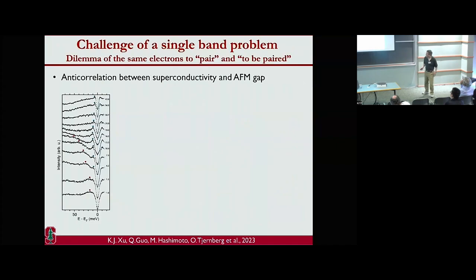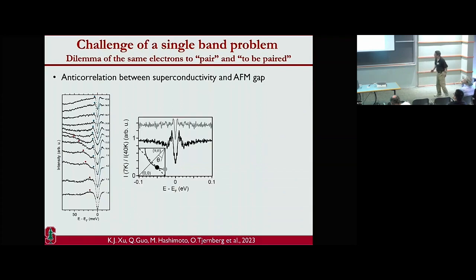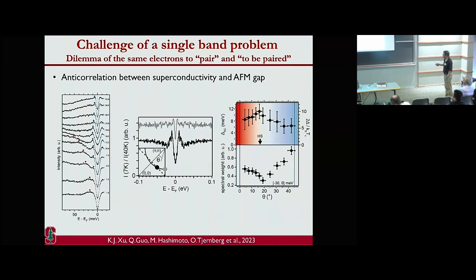The next thing you can see, I'm going to go around the entire Fermi surface. You can see that this is the red feature, the antiferromagnetic feature, coming in around the node. But consistently inside, there is a Bogoliubov quasiparticle in this system, and the Bogoliubov quasiparticle has its coherence peak showing its maximum also at the hotspot. At the position of the antiferromagnetic hotspot, the pseudogap is the largest, but the system was clever enough to also build the strongest superconductivity. They're all at the same spot.